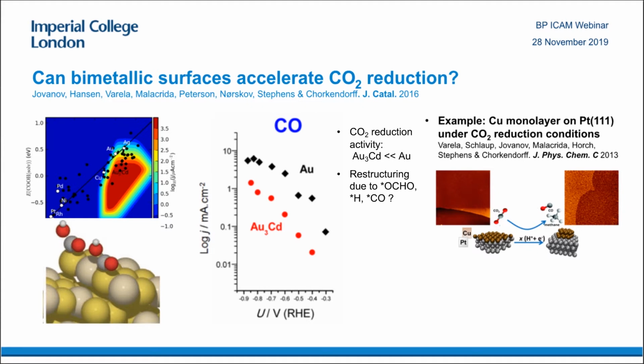Here we were observing it using electrochemical STM. As soon as we put CO2 there, CO2 produces CO, and CO pushes the copper aside, you form islands and expose platinum. So we really observe directly that the catalyst restructures a lot under reaction conditions. It's something to bear in mind when you're looking at these multi-component catalysts.